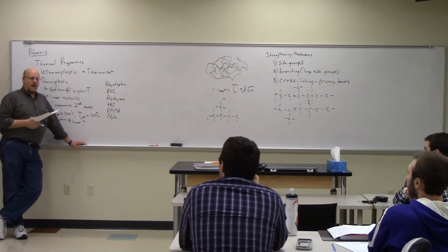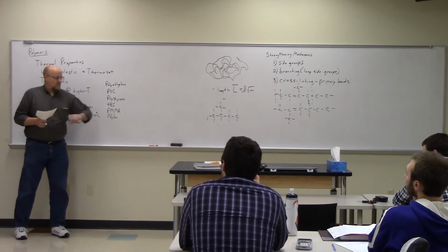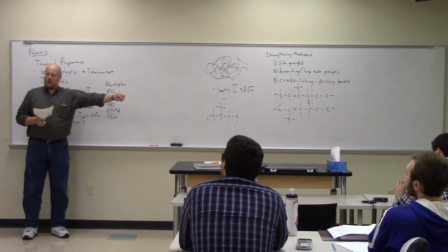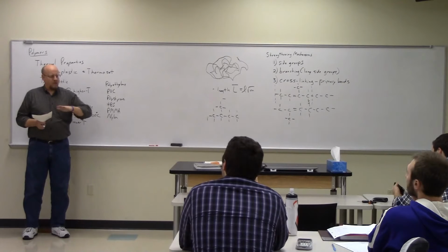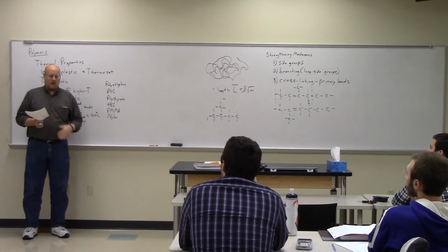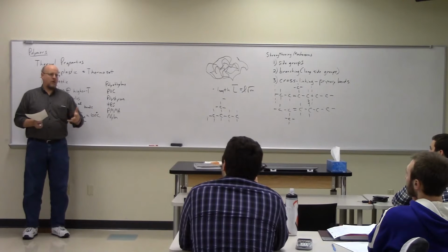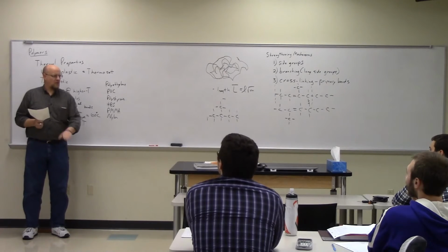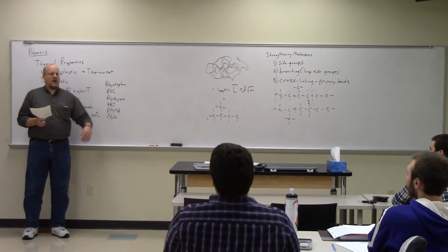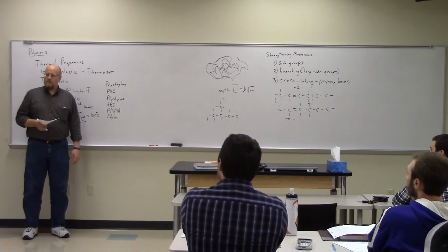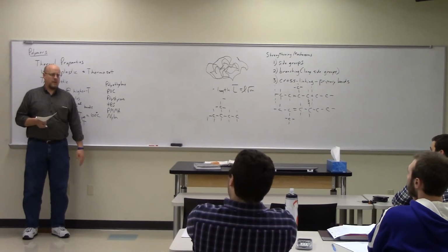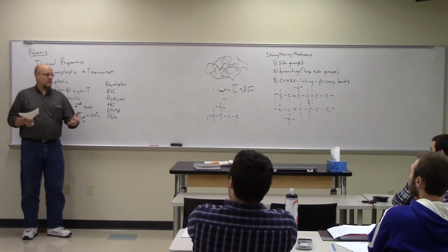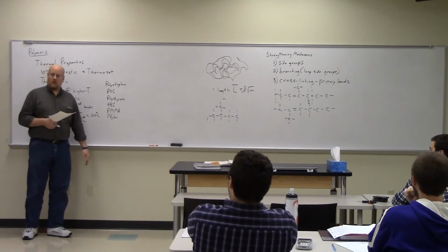But we have a plastic bender down in the machine shop. It's basically nothing but a high resistance electrical bar, a bar that gets hot when you pass current through. You just put a sheet of plexiglass over the top of it, and the heat radiates off the bar onto the plexiglass. It's not so hot I can't touch it. I wouldn't leave my hand on it, but I could touch it without burning myself. But it gets it hot enough that you can then bend the plastic. And then you just let it cool, and it hardens up again. Okay. So you can bend acrylic around the corners of your box.